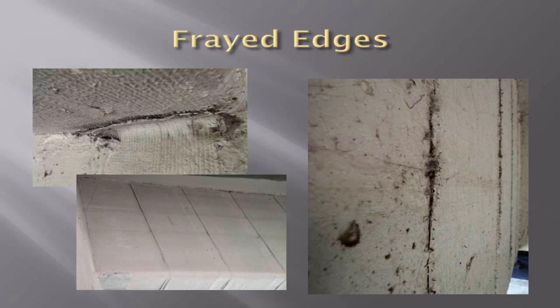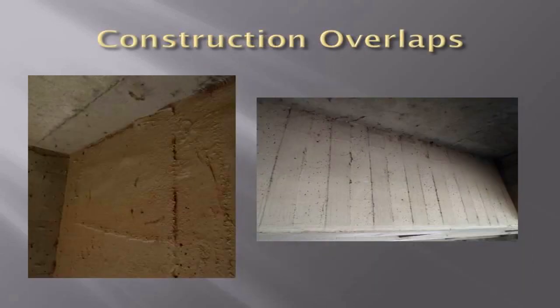Frayed edges, it seems kind of benign, isn't a problem, but according to national federal guidelines, a frayed edge is at the end of a member, and it should be considered critical, although it's fairly common. Once again, more pictures of poor surface prep, minor delaminations on the edges just from a lack of saturant. Construction overlaps, although in these pictures you don't see any problems arising from the construction overlaps, but it's an area that should be monitored.